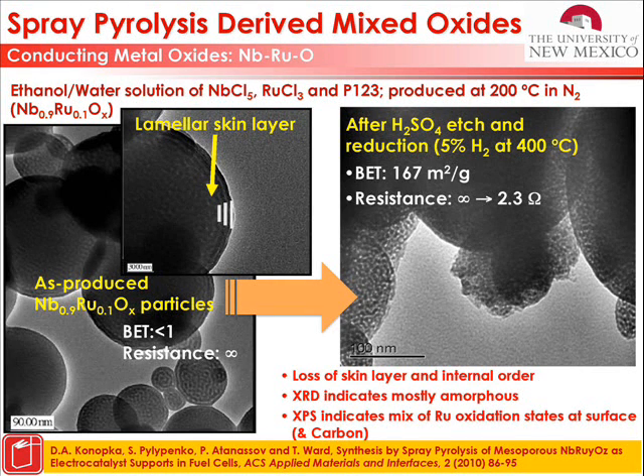Because ultimately, in your catalyst, you want to have as little things possible in the reaction mix for a one-pot synthesis. All these beautiful things like surfactants and other stuff that people use to make things beautiful, they are absolutely a no-no in the industry because they're very difficult to get rid of afterwards. So from a practical engineering standpoint, the simpler, the better from the point of view of manufacturing. So here you have simply a salt of platinum and ruthenium, in this case, dissolved together with the carbon suspension and passed through the reactor.